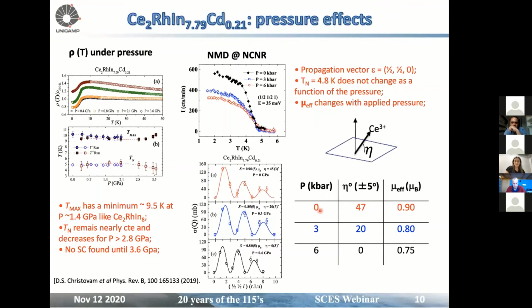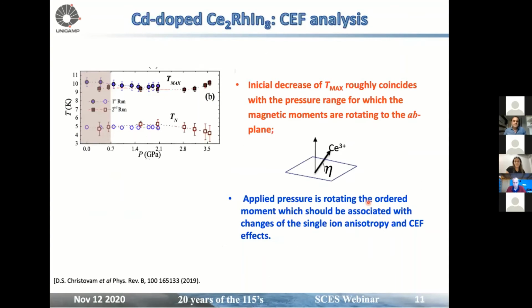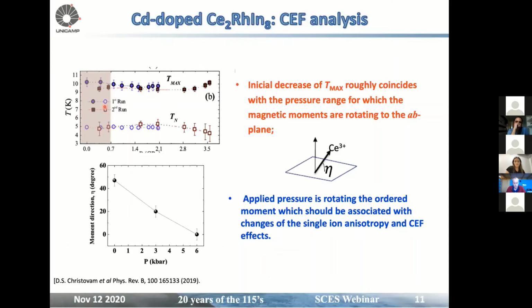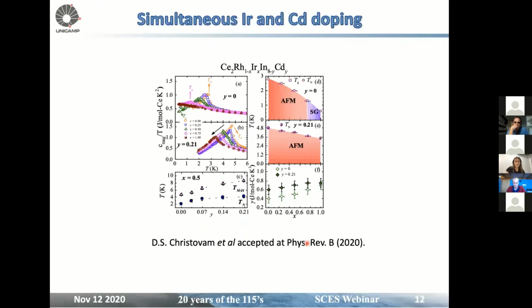So as pressure is increasing, moment is decreasing, and the moment direction is going toward the AB plane. So what we could see is that the initial decrease of Tmax roughly coincides with the pressure range for which the magnetic moments are rotating to the AB plane. So applied pressure is rotating the ordered moments, which should be associated with a change in the crystal field anisotropy. And then we continue our work.